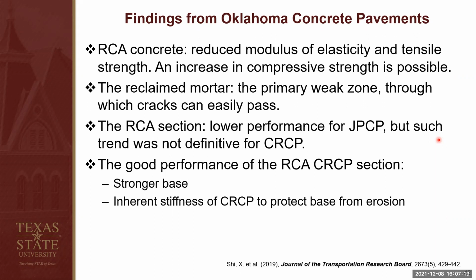We concluded the good performance of RCA CRCP was due to the stronger base. Remember, for the RCA CRCP, it was built on asphalt concrete base, which was much stronger than the soil base for the JPCP section. We also think using CRCP, the pavement type, will also help the concrete pavements containing RCA. The steel rebar can help protect base from erosion, which is very important for the RCA concrete because our slab is less stiff compared to the control slab. So that's why we need to make sure the base is protected by using the steel.